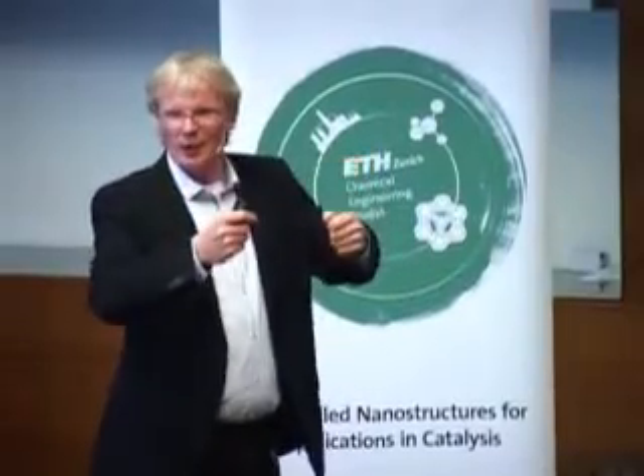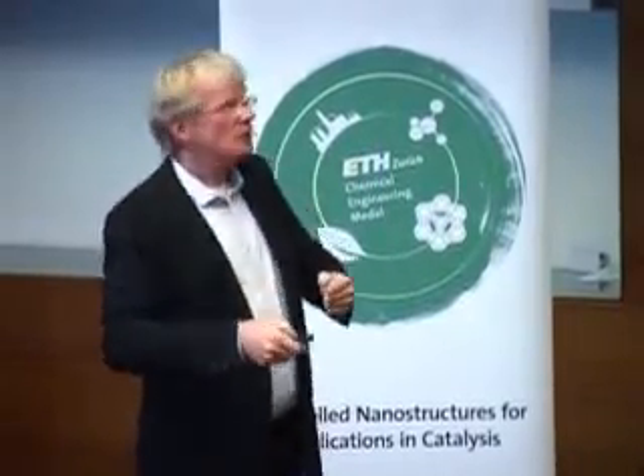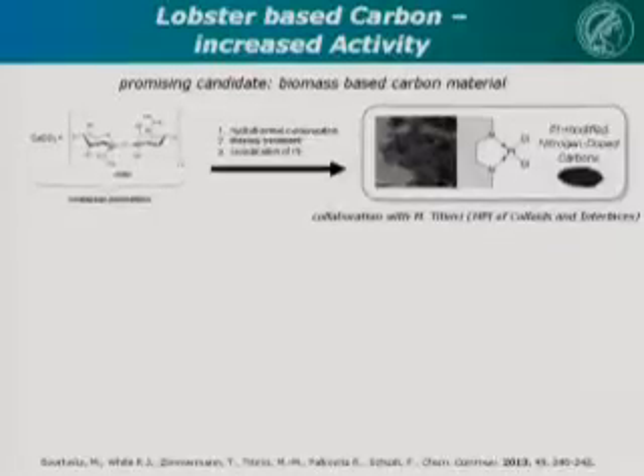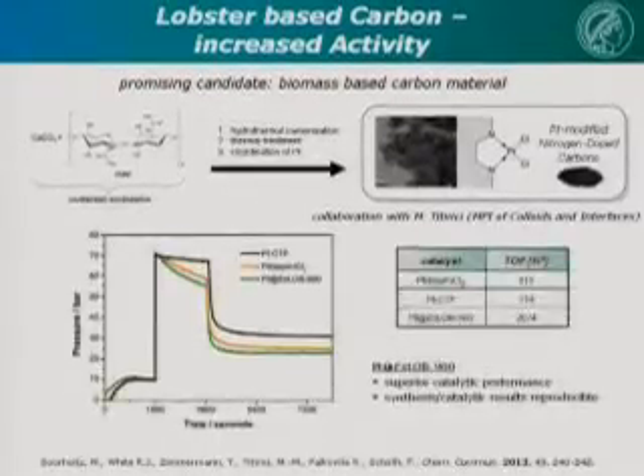They actually collected lobster shells, heated them, high temperature, protective atmosphere, and got a black material. We threw platinum on it, and indeed, the catalyst had an activity which was twice as high as the activity of the molecular platinum bipyrimidyl system Periana had described, and it's very reproducible. When we first had the result, we said, well, this may have been a very special lobster. Get a lobster from a totally different region in the world, do it again.